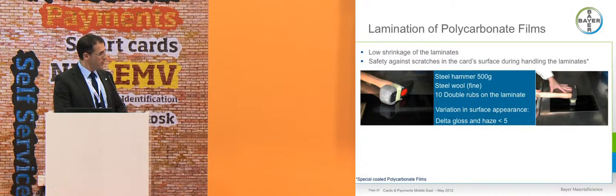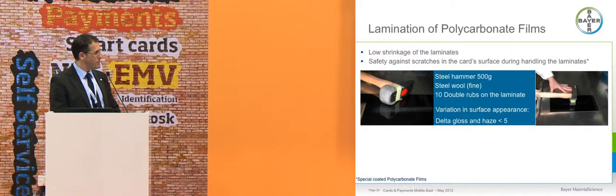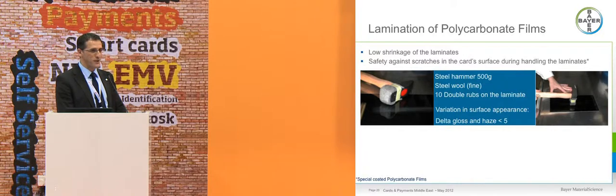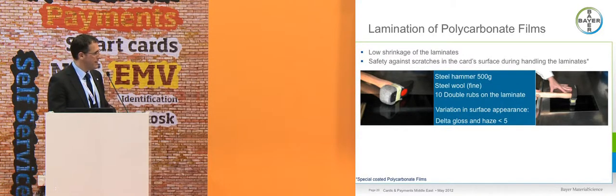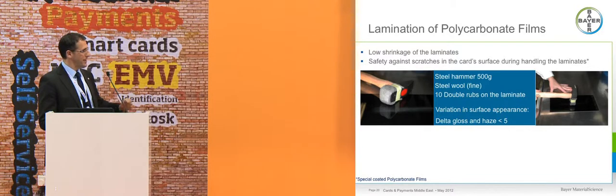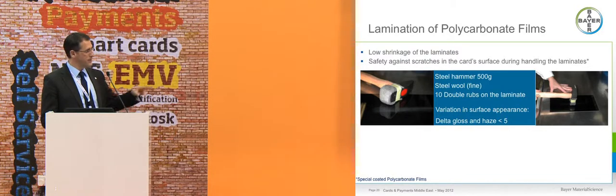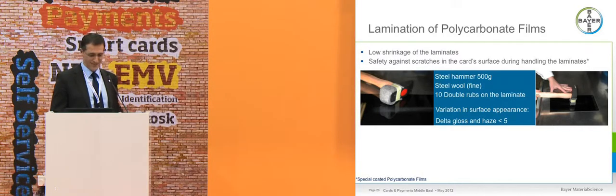Here is a very simple way to evaluate the scratch resistance of a polycarbonate laminate. Very easy with a hammer and some steel wool, just by wrapping it around the hammer and doing 10 double rubs. We say that with our films, the delta in the gloss will be less than 5 units.